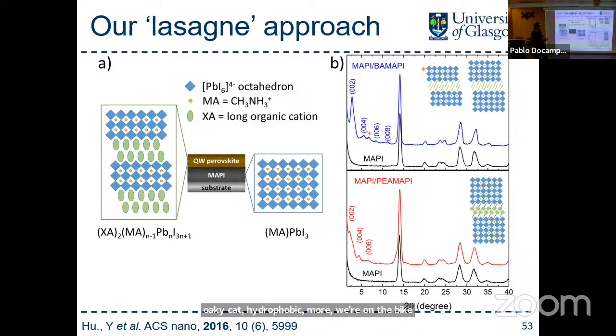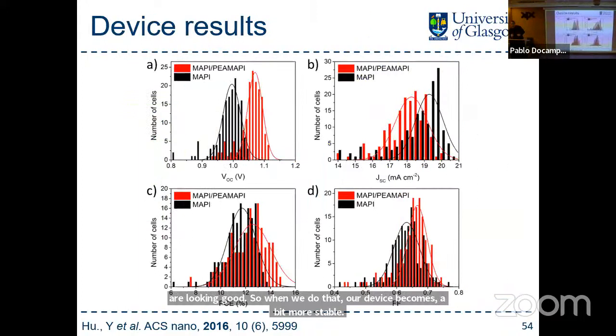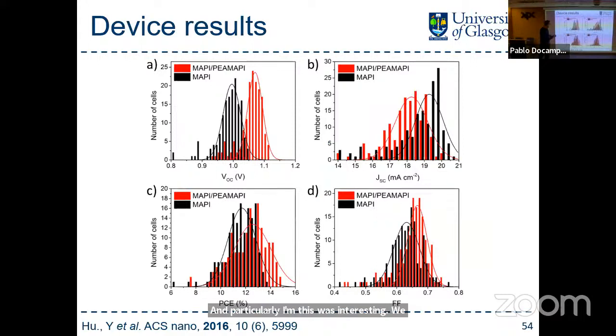So when we do that, our device becomes a bit more stable, and particularly, and this was interesting, we saw an increase in the open circuit voltage. That's 100 cells of the same type. Because normally with these devices, the device-to-device variability is high. So you normally go, okay, you short it once, make sure that actually holds for a large number of devices.